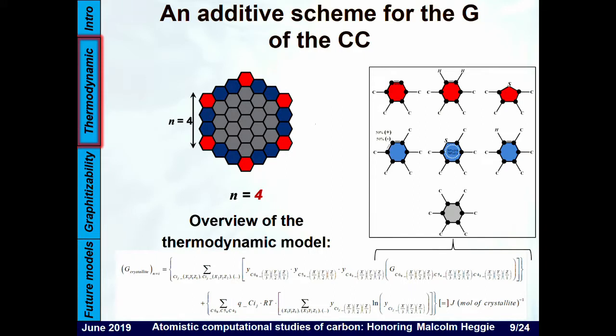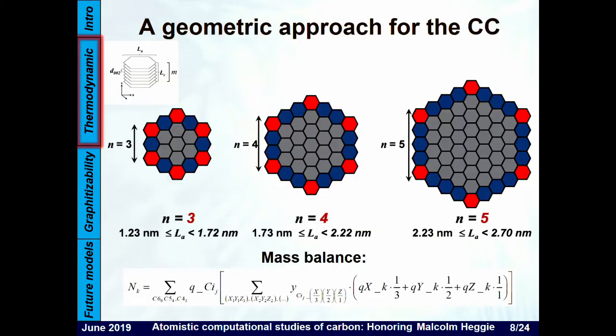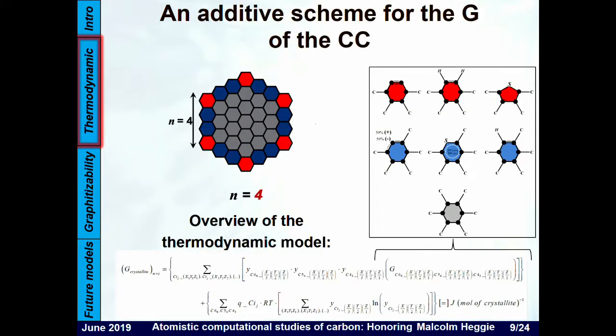After that, what we do is that we estimate the Gibbs energy of the composing species which can go on each of these hexagons. We use a simple additive formalism with a thermodynamic path to estimate both the enthalpy and the entropy. And after that, you use this final equation, which is very simple. It's only big because there are a lot of precise terms to be written. But essentially, you put this one here, and this one here. You sum it all, and you estimate the Gibbs energy of the entire structure. After that, you stack them up, and then you obtain the Gibbs energy of your co-crystallites, which, based on our second hypothesis, will define the Gibbs energy of the graphitizable carbon.